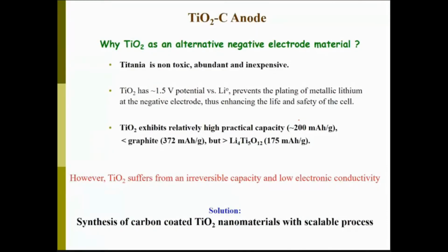Let's focus and see how we can make one unique material with one single precursor without using any solvent in a lab. For example, TiO2 as an anode material. I showed in the cartoon, the graphite was used as an anode, but this material also can be used as an anode material. The titanium is used in the solar cell, which is a semiconducting material. So there should be conductivity, and that is the reason we add a small amount of carbon layer on the top of TiO2, where the electron can hop effectively, and we could create an original core shell architecture that will give you enough capacity, and at the same time, the batteries could be safe.